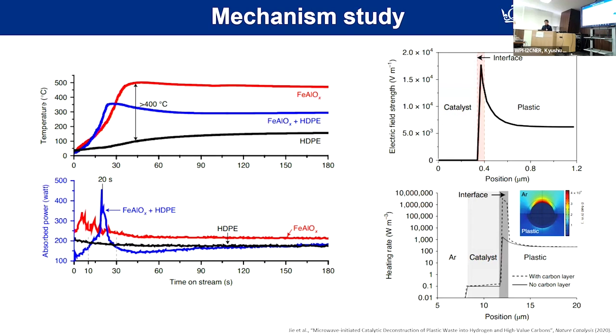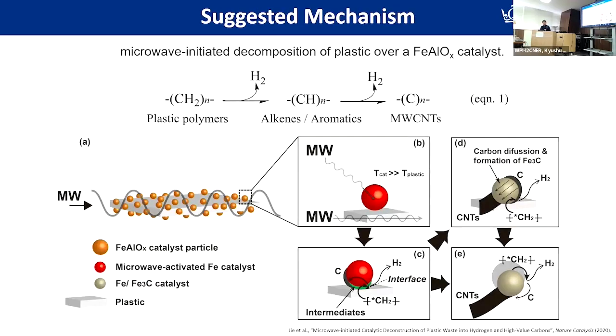And when the carbon is formed at the beginning on the interface, it will also cause a rapid heating rate at the interface, and this could be reflected in the absorption power change because of the carbon radical formation.